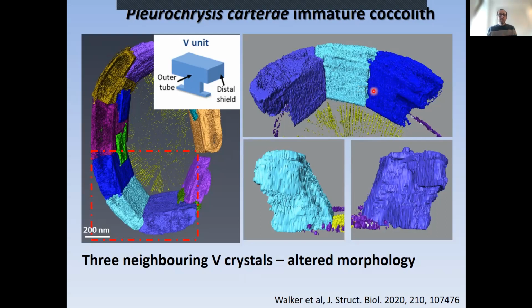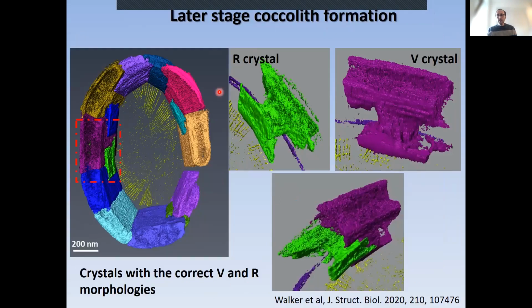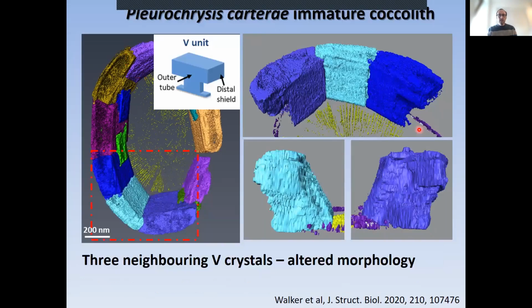If you look at the back, where normally this crystal is going to be very thin, I can show it here. It's very thin here at the back. It's just a uniform thickness because you are lacking a part of our crystal growing from behind that is restricting the growth of this crystal backwards towards the outside of the coccolith ring. And same thing in this purple one here.